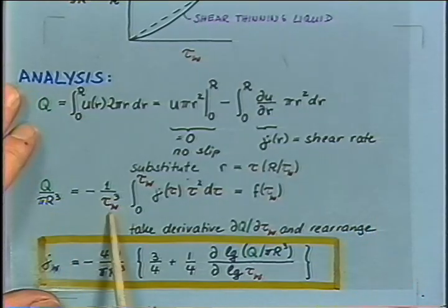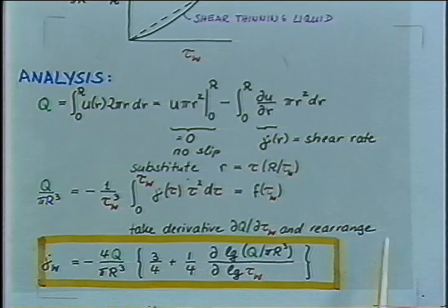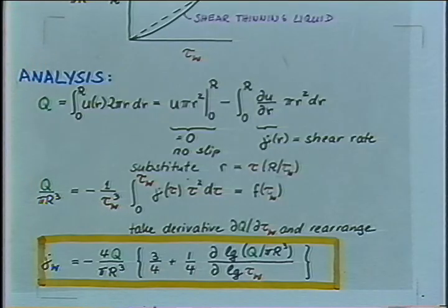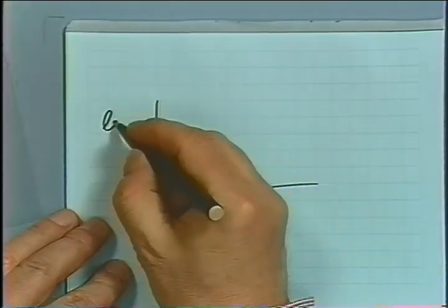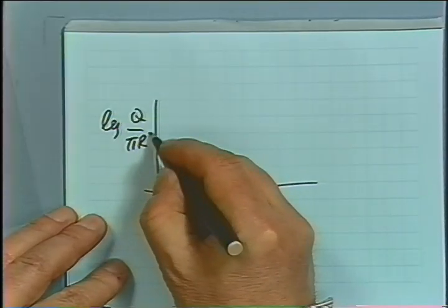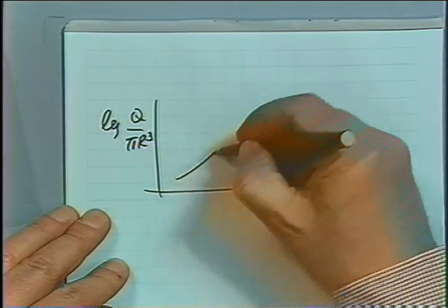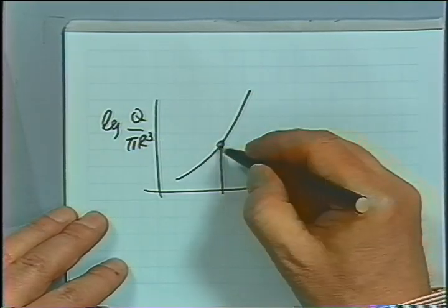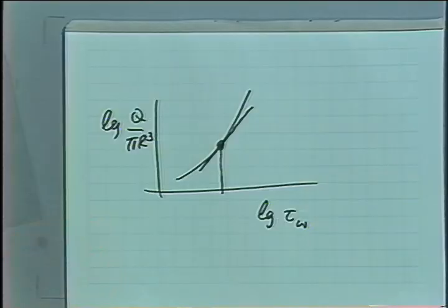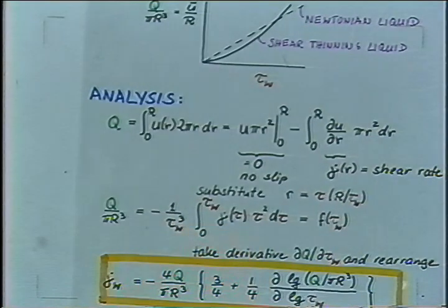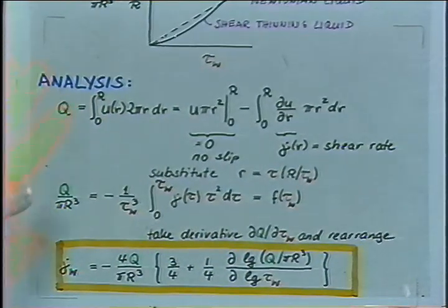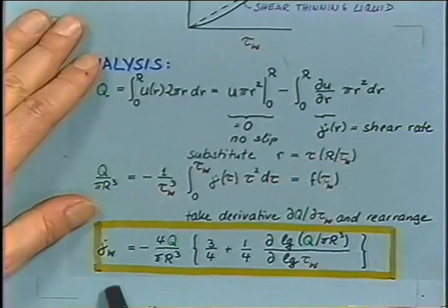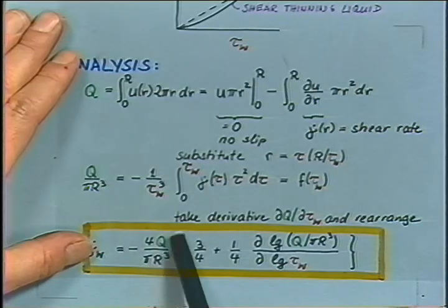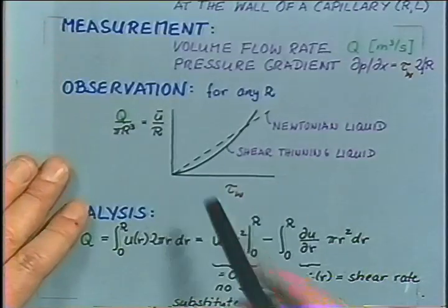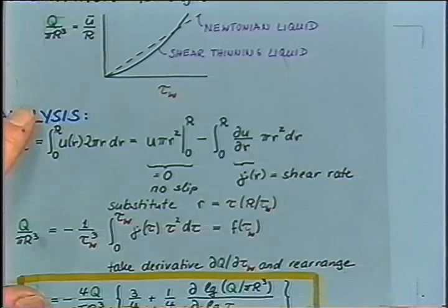Now, we can take the derivative of this function with respect to the wall shear stress. Let me draw this here for a moment. We would have a function where we have log Q divided by pi r cubed and log shear stress at the wall, and we would have this function from our experiment. We would take one data point here, and we also would take the slope at one point. And this slope is what we are going to calculate. We take the derivative and find that after all rearrangements, the shear rate at the wall itself is just a function of Q over pi r cubed. Factor 4 is coming in, so it's basically this value here, and it is multiplied with a function which contains the gradient.